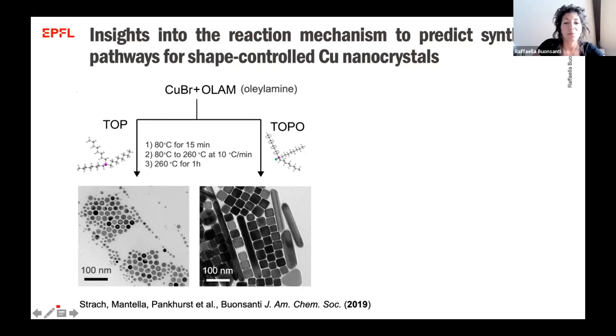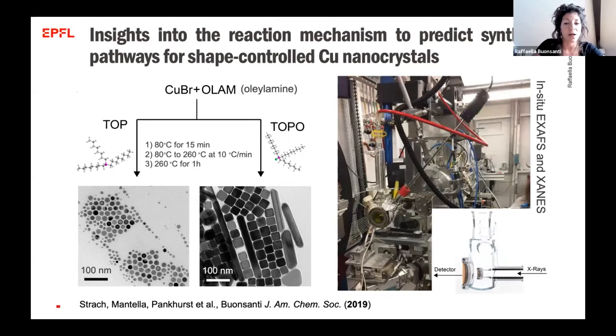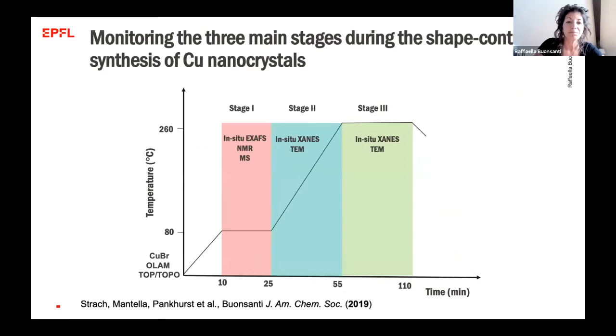Of course, we could have stopped here and just said that this is because the trioctylphosphine and the trioctylphosphine oxide bind differently to different facets of copper. But this time we really wanted to learn more about the chemical transformation behind the formation of copper particles. And so we built a flask which really resembles the flask that we use in the lab, and we went to the synchrotron to perform in situ X-ray studies.